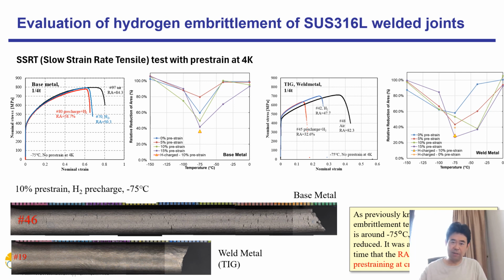One factor is martensite transformation, which occurs on the low temperature side. And the other is hydrogen diffusion, which is active at higher temperature. So this competition makes this the most deteriorated temperature condition. In this project, we carried out many SSRT tests with pre-straining pretreatment. This is a very new point, a novel point.